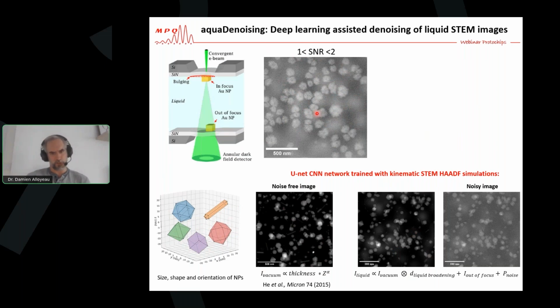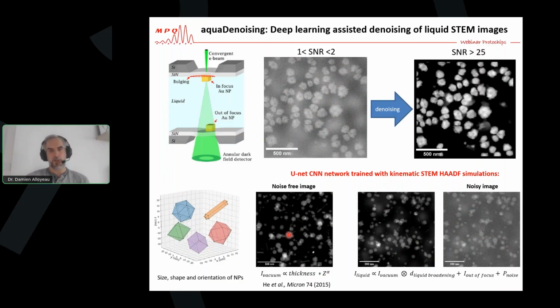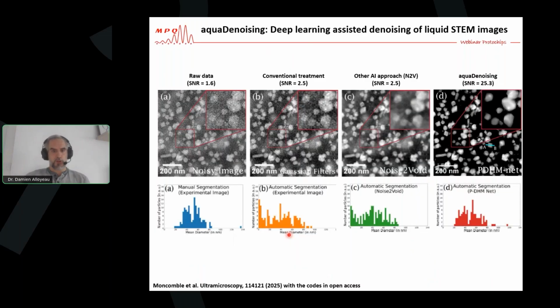Then you have to take into account the noise of your image. To do that, you add the out of focus nanoparticles, and you take into account the liquid broadening by changing the convolution of your probe, and you add a Poisson noise. And you end up with those noisy images that are very similar to your experimental images. When you have a UNet network, you give it the noisy image and the noise-free image, and you train it to optimize the noisy image. Now it's able to give you these liquid cell TEM experiments with a much better signal-to-noise ratio.